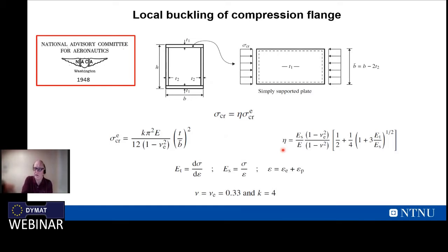And now you see that this correction factor is a function of the secant modulus and the tangent modulus. The tangent modulus is given like this. The secant modulus is given like this. When looking at this formula, you clearly see that when you are going to do a numerical simulation and you have folding, buckling of thin wall components, it's totally wrong to use a bilinear stress strain curve. You need to be very careful to quite accurately model the hardening of the material. This is very, very important. If not, you can get a totally different deformation mode.